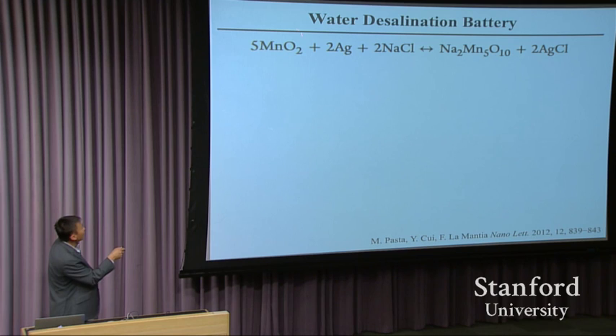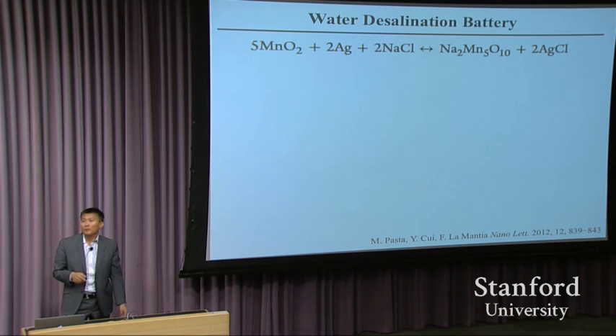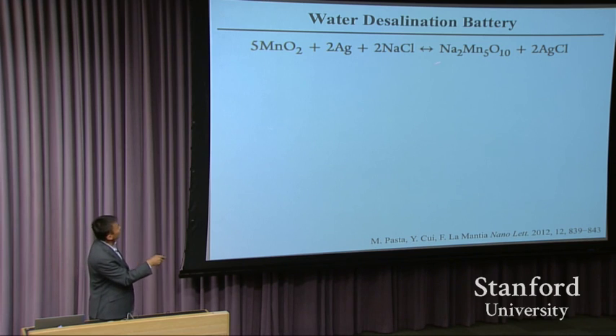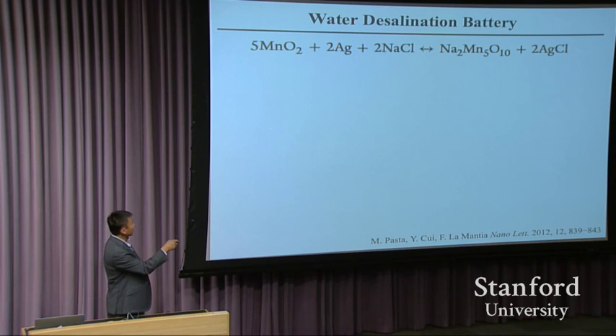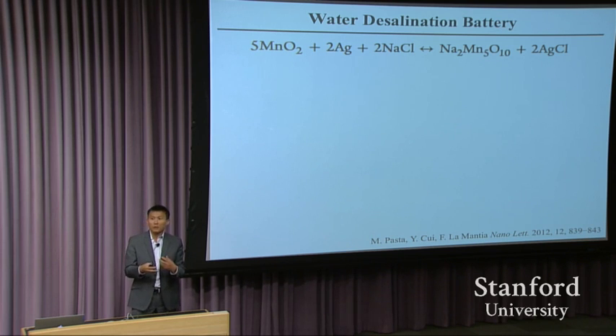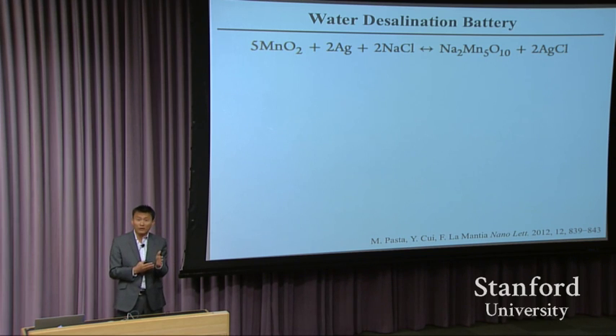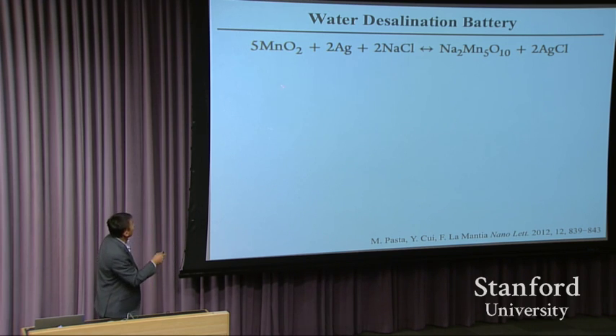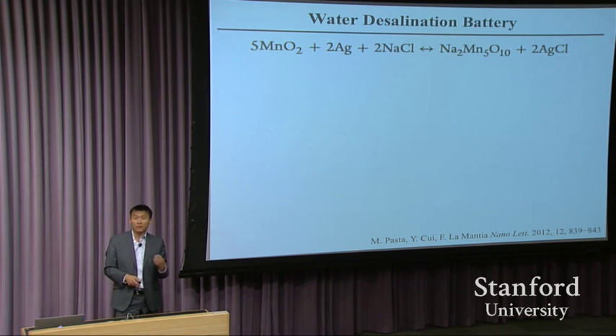So we identify two materials right here. One is a low-cost manganese dioxide. The manganese dioxide can take sodium in. This is sodium chloride from seawater. And the silver can take chlorine out, forming silver chloride. The silver and silver chloride reaction is very well known, and a very common use in electrochemistry. The so-called reference electrode is silver and silver chloride interconversion back and forth, very reversible. And manganese dioxide is also known to take sodium in and out reversibly with very little energy loss.